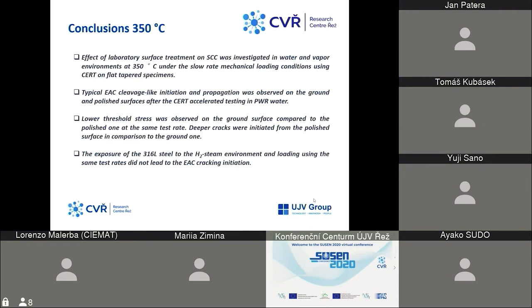So to make a bit of summary, after testing at the same temperature in two different environments with two different strain rates, we can say that typical cleavage-like initiation and propagation was observed on the ground and polished surface after testing in PWR water. The lower threshold stress was observed on the ground surface compared to the polished one at the same strain rate, but deeper cracks were initiated from the polished surface in comparison to the ground one. Also, after the exposure of this steel to the hydrogenated steam, we used two different test rates. We didn't find any EAC cracking initiation.